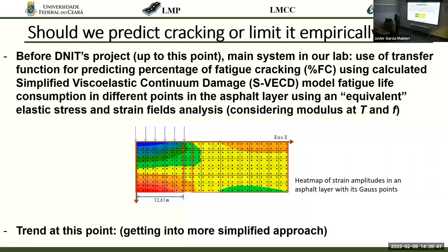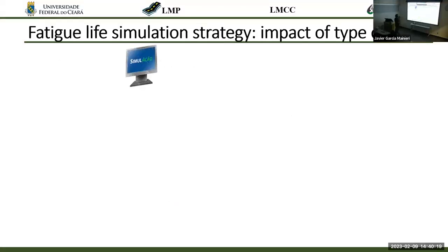And for now we use that, but for the materials, we get a very complex model, but for the calculation of strains, we do not do that. This was our decision in order to have very fast calculation in the computer. So the only thing we do is that we take into account the traffic speed and the temperature in order to calculate the distribution of stress and strain. This is it. And I can say the trend at this point of the project is that we get even simpler, because this is already too complicated for pavement calibration. And this is why we are trying to get simpler.